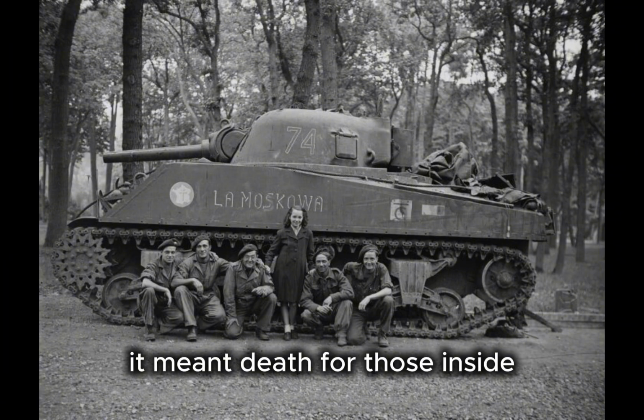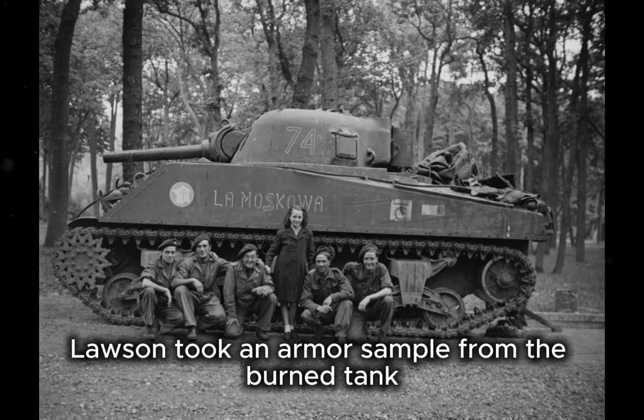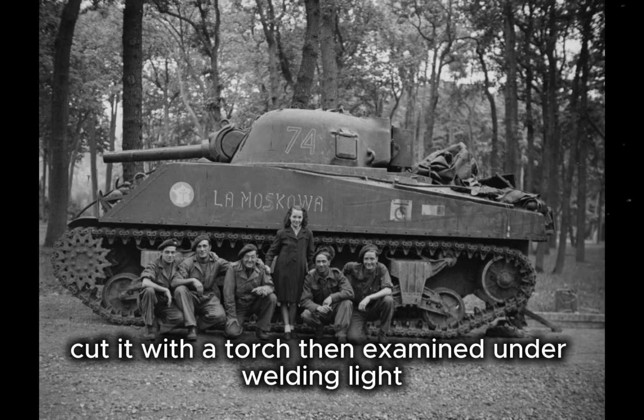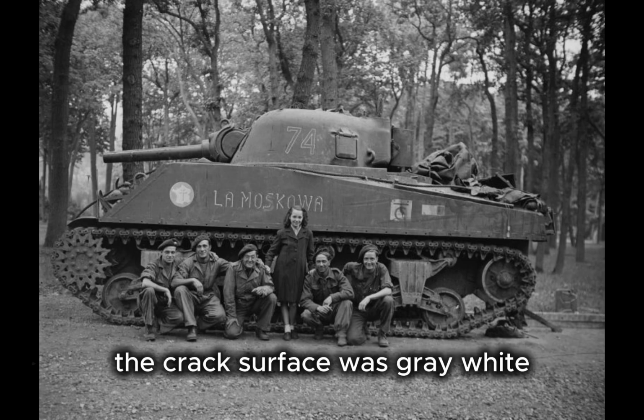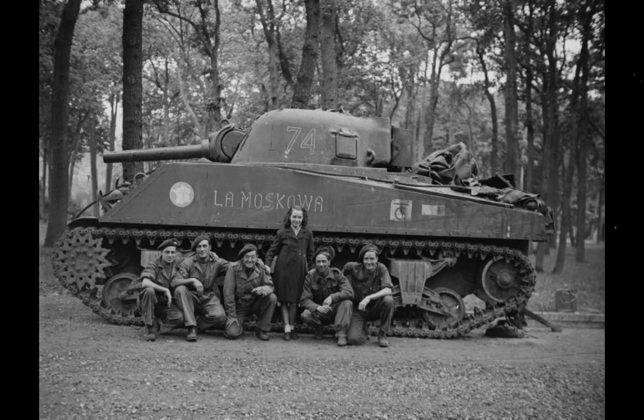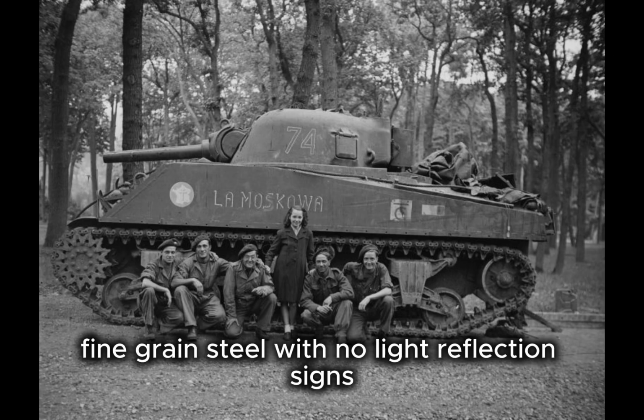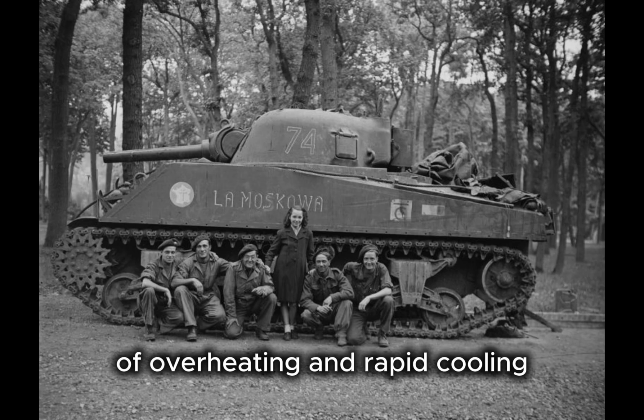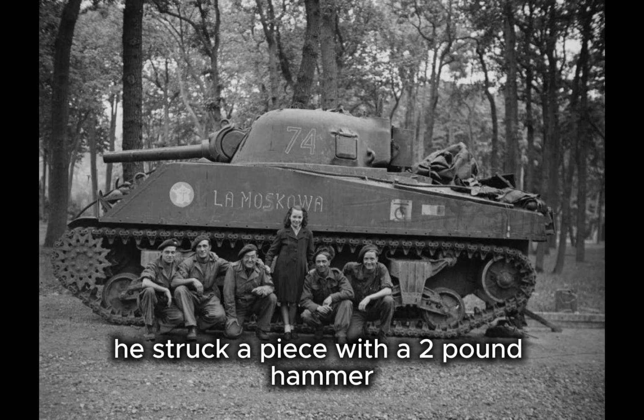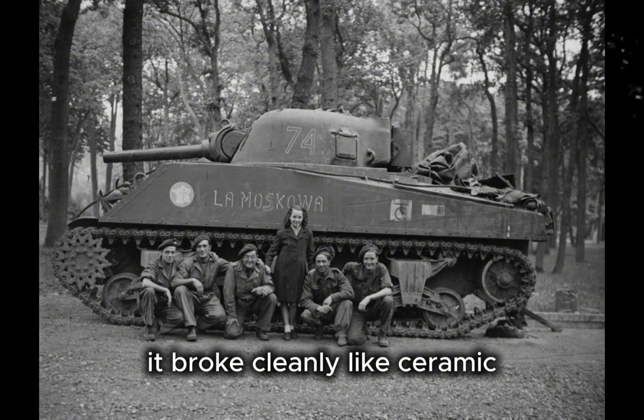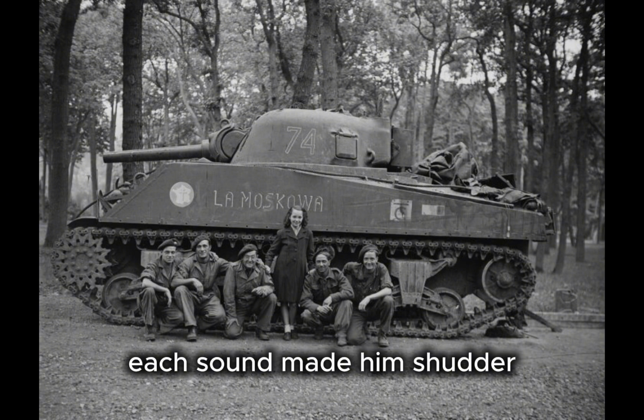That 28% meant thousands of tanks shipped earlier, but now, on the Normandy battlefield, it meant death for those inside. Lawson took an armor sample from the burned tank, cut it with a torch, then examined under welding light. The cracked surface was gray-white, fine-grained steel with no light reflection, signs of overheating and rapid cooling. He struck a piece with a 2-pound hammer. It broke cleanly like ceramic. Each sound made him shudder.